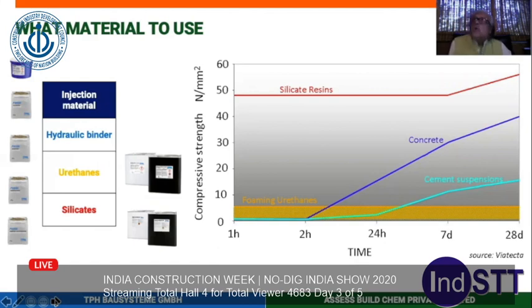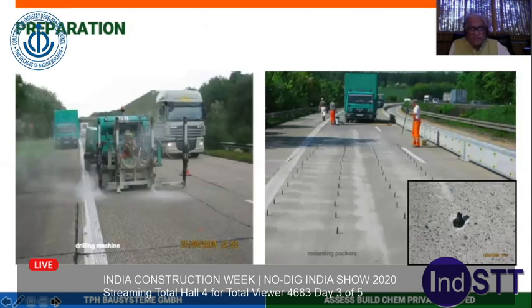If you use a good concrete, after 2 hours it starts setting. But before that 2 hours, if the water pressure is high, it can be thrown out. But if you use the silicate resins, you can see within 1 hour or within 2 hours, it can develop a strength of up to 50 newtons. It is very important to select the type of material. This is where it is settled.